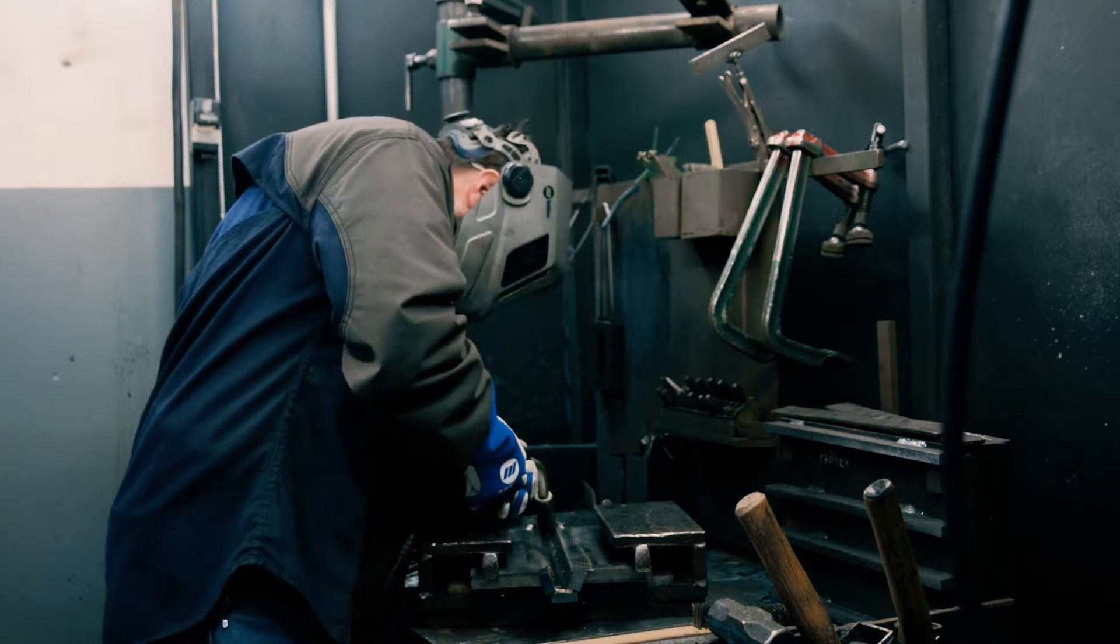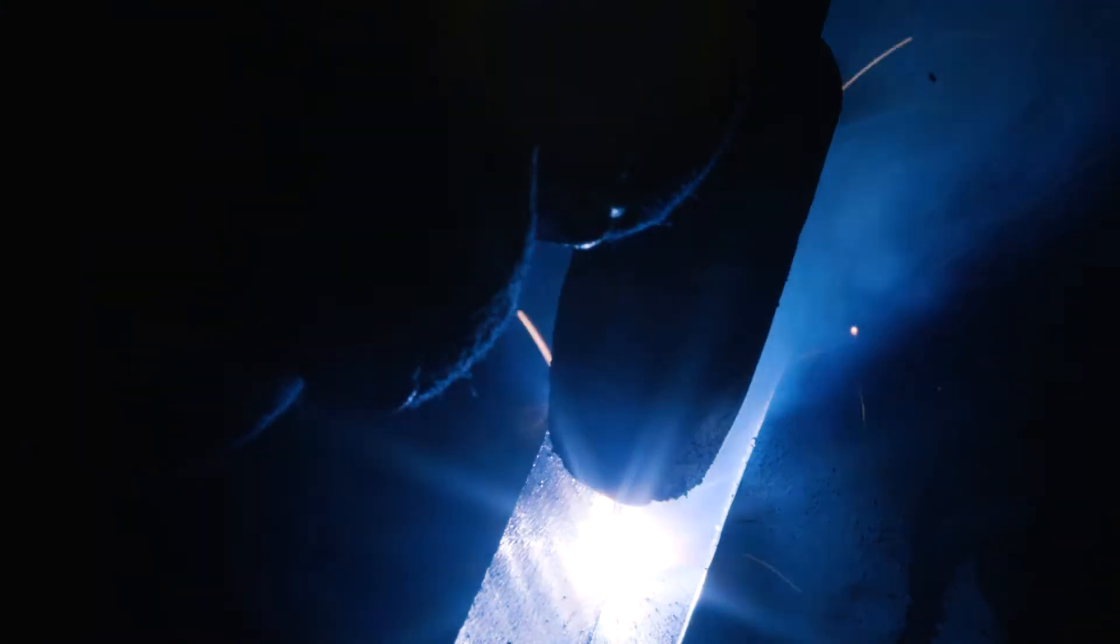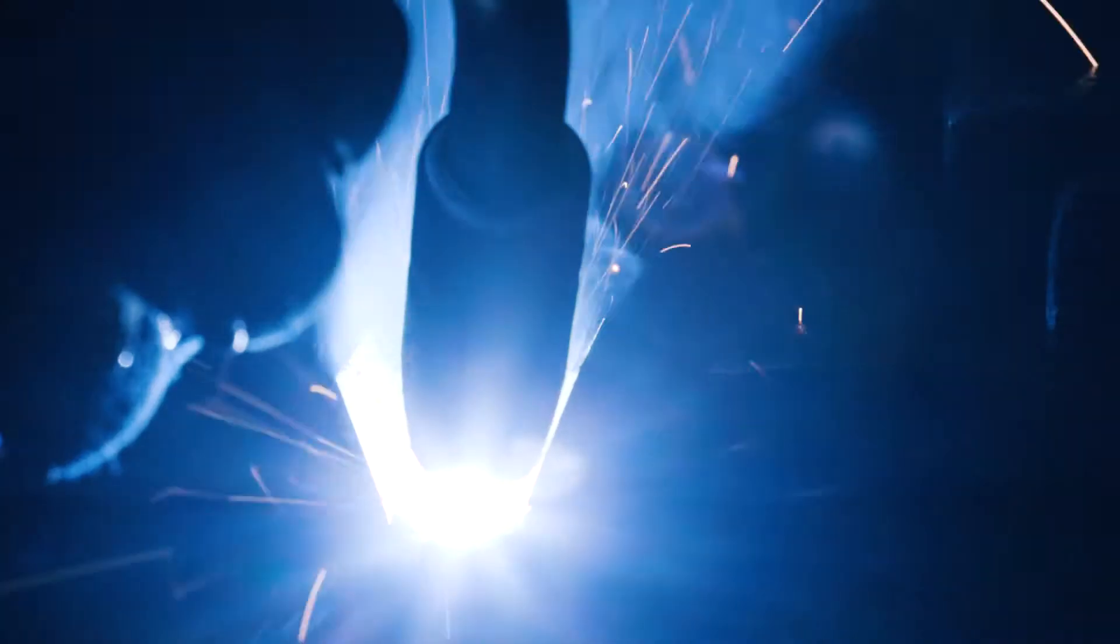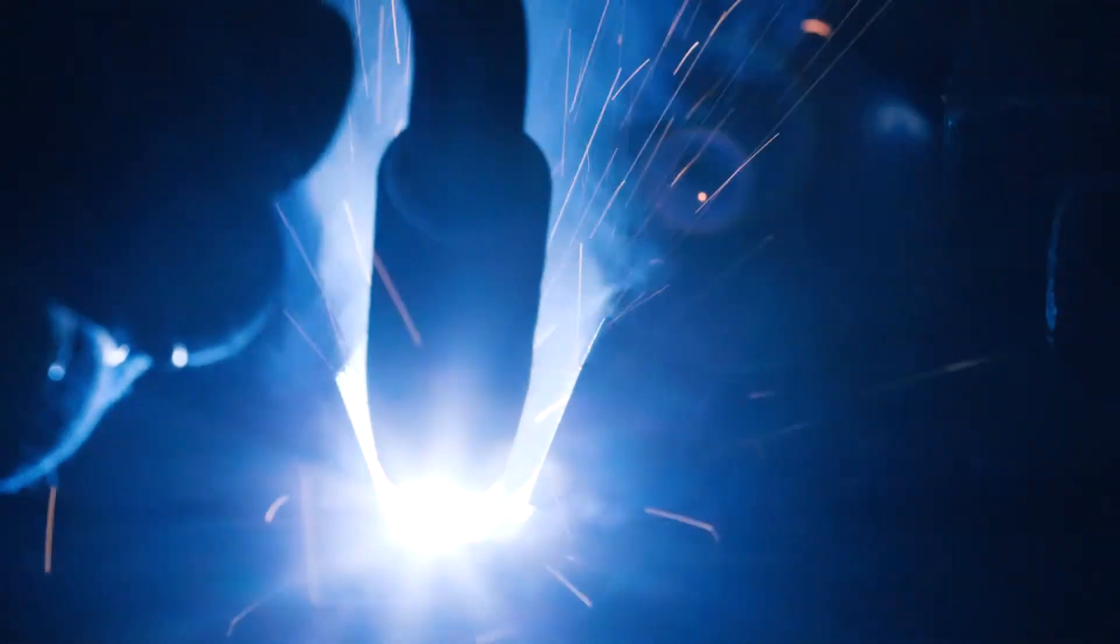The technician then begins to weld the plate. In between passes, the technician records the pass sequence and welding parameters, such as travel speed, amperage, voltage, and wire feed speed. The technician then waits until the plate has cooled to below the maximum interpass temperature before welding is resumed.